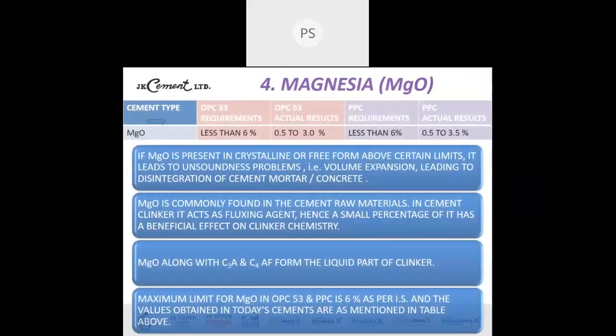Fourth parameter is the magnesia content, MgO. Now, MgO in OPC 53 should be less than 6%. The actual result range in India is between 0.5 to 3%. For PPC, the requirement is the same. It should be less than 6%. We get a range of 0.5 to 3.5% for MgO.